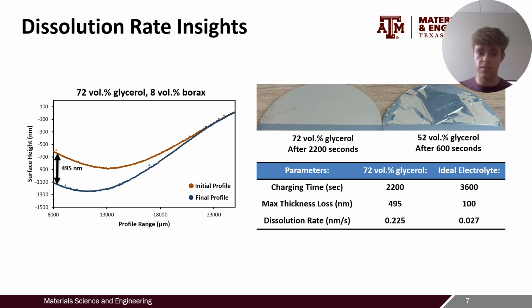It is also worth noting that this measurement wasn't done with the 52 volume percent electrolyte, since it completely degraded at least 10 minutes in, probably around 8 minutes. And this was just a completely insufficient charging time for neutron reflectometry in the future. But using the 72 volume percent electrolyte, it had an approximate dissolution rate of negative 0.225 nanometers per second, which on first look actually sounds pretty good.